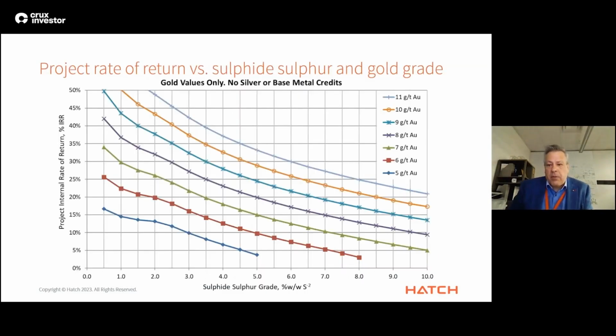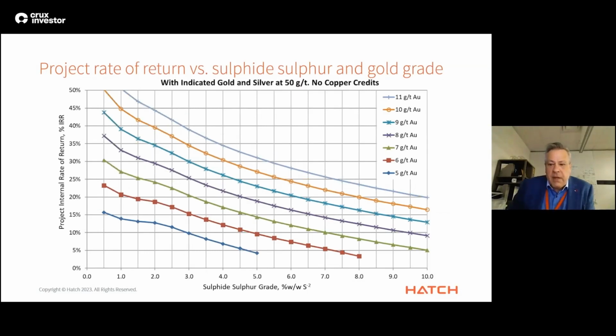This figure, for the base case, shows the internal rate of return on the y-axis as a function of weight percent sulfide sulfur grade on the x-axis for gold grade ranging from 5 to 11 grams per ton. Obviously, the IRR increases relatively proportionately with gold grade, but decreases with increasing sulfide content as the operating costs of treating sulfide increase. In this figure, we see the impact of adding silver at a grade of 50 grams per